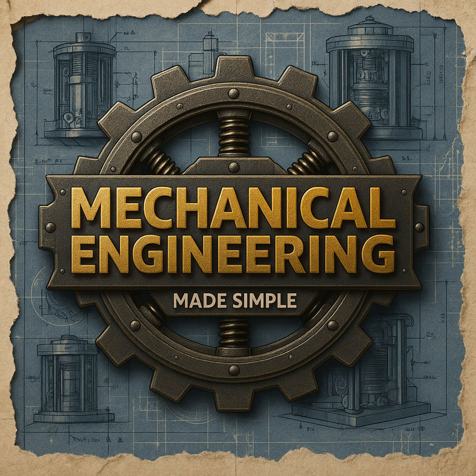In modern bioprocessing, engineers use orbital autogenous welding for tubing. Autogenous means welding without adding any external filler wire. A computer-controlled machine clamps around the tube and orbits a tungsten electrode around the joint, melting the two tube ends together purely with their own base metal. Okay, so it's a machine doing it.